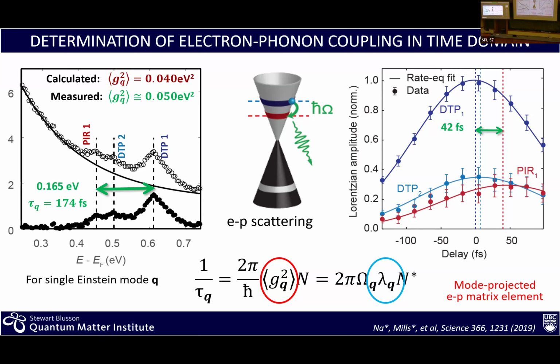But if you fix both K and Q, then theoretically it should be just a delta function peak, right? So where does the width come from? Well, the width comes from the fact that we have resolution of the order of 20 femtoseconds and 20 meV. This is sort of a challenge where, depending on what you're after, you may or may not have that resolution.